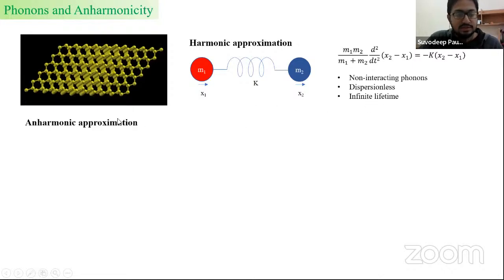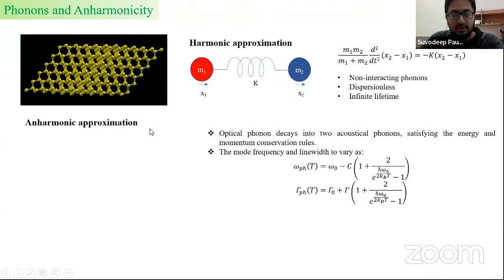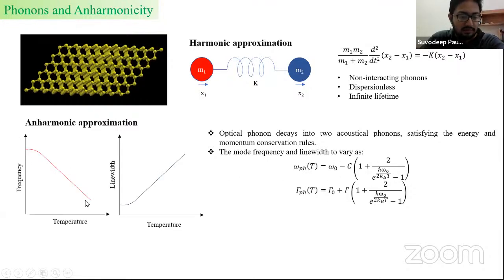But in a more realistic scenario, we consider the anharmonic approximation, where the interaction of phonons with other phonons is allowed, and therefore they have a finite lifetime. So essentially what happens is the optical phonons decay into acoustical phonons, and this theory is manifested as a temperature dependence of the frequency and line width, which are shown by these equations, which are also shown by these curves.